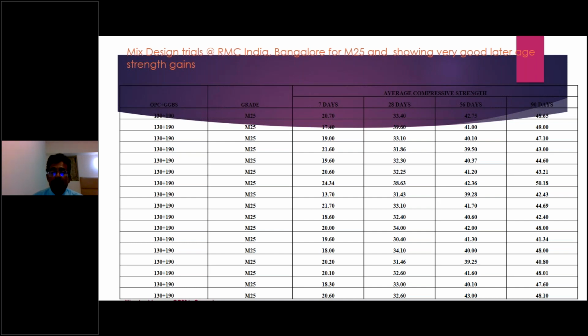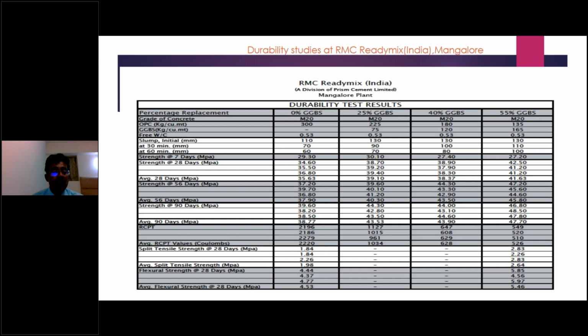For M25 grade concrete, the 28 days compressive strength average is about 32, 33 MPa. But the 90 days compressive strength is almost 45 MPa. That is the beauty, the gain of compressive strength over time with higher replacement of GGBS. Similarly, the durability performance is very good. RCPT value with a higher replacement of 50% comes to between 600 and 500. Splitting tensile strength improvement is there. Flexural strength improvement is there, compared to the pure OPC mixes.